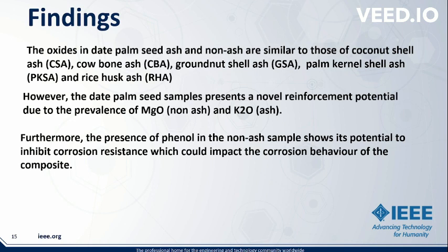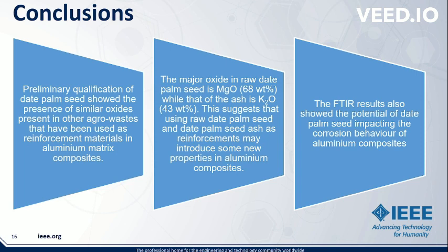In conclusion, preliminary characterization of date palm seed showed the presence of similar oxides present in other agro wastes that have been used as reinforcement materials in aluminium composites. The major oxide in the raw date palm seed is magnesium oxide, about 68%, while that of the ash is potassium oxide, about 43%. This suggests that using date palm seed and date palm seed ash as reinforcement may introduce some new properties in aluminium composites.